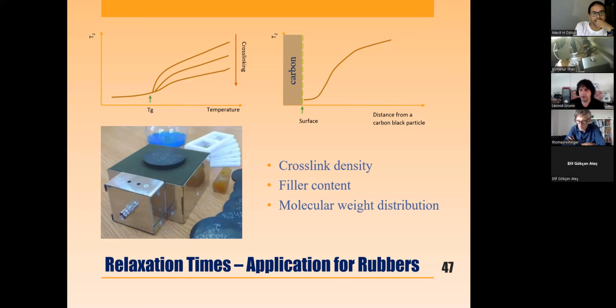No, it depends on the high resolution instrument. High resolution NMR can be just the classical high resolution NMR for liquids and also a solid state probe in the wide bore magnet. And then for spectroscopy, it must be rotated under magic angle, and cross polarization can be implemented to look at the carbon nuclei. But it depends on the type of the probe and the amount of sample. Normally, if you go high with frequency, you get stronger signal, and you have much better signal to noise. This can be the advantage. So the free induction decay signals should not differ much depending on the frequency. Okay. But the T1 measurements, of course, are a different story.